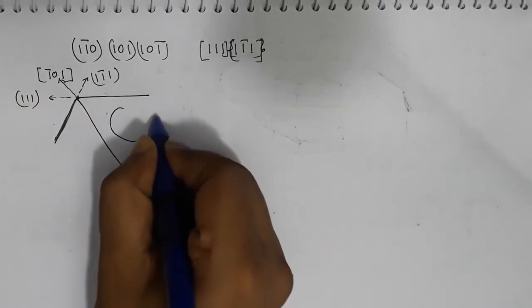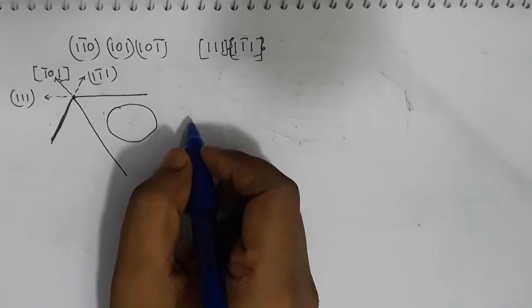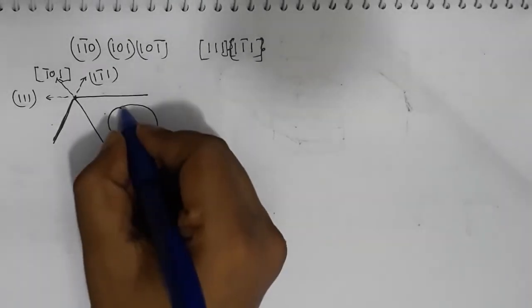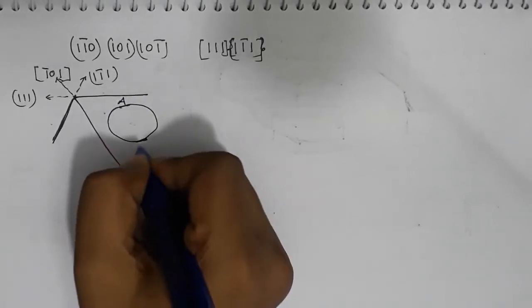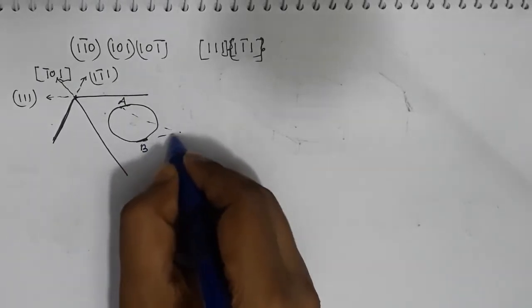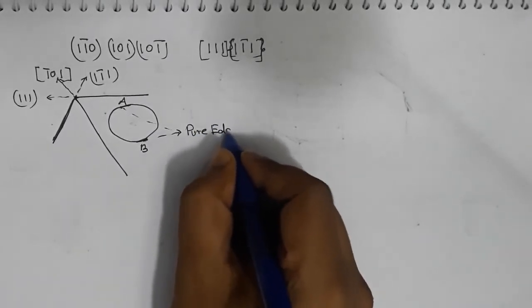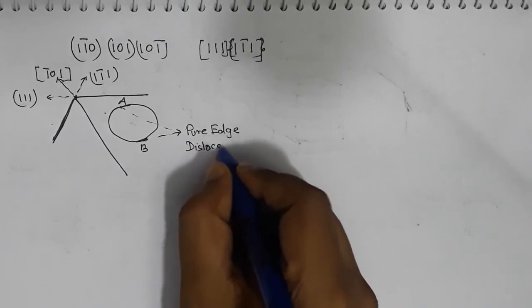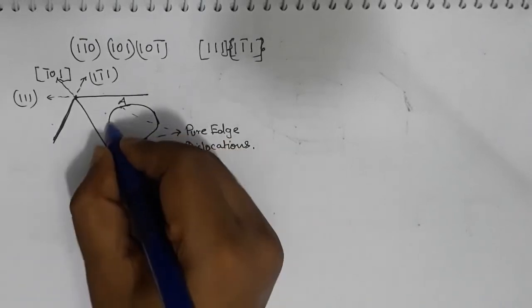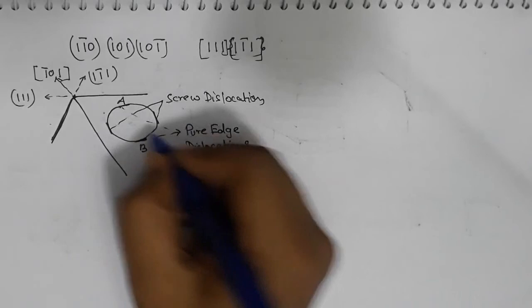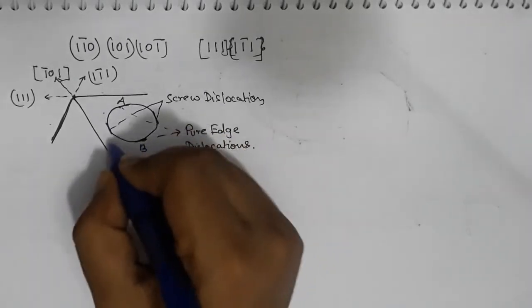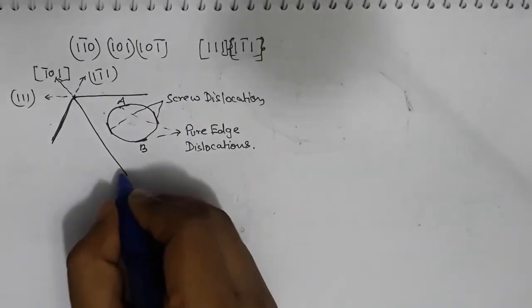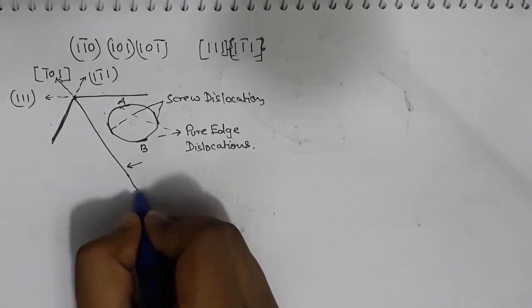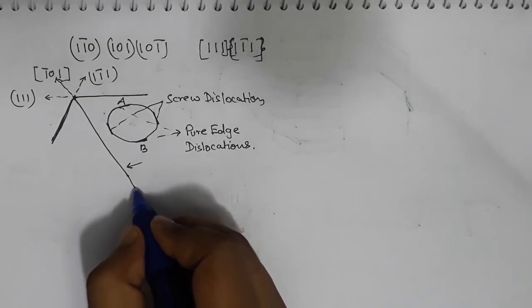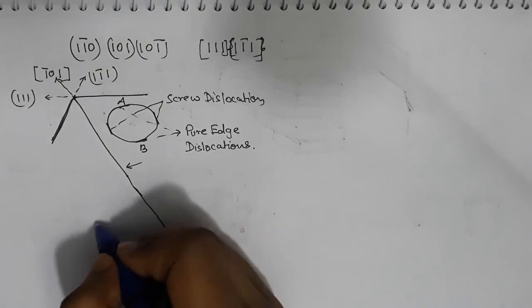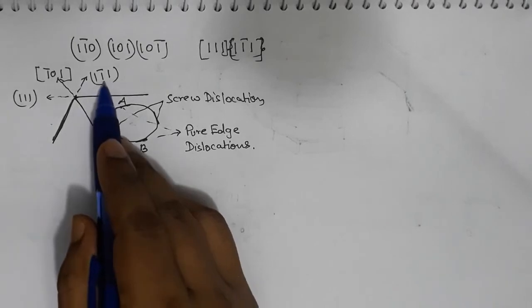Now you have a dislocation loop. The dislocation loop is such that here and here, let's call them A and B, these two are pure edge dislocation parts. And here and here you have pure screw, and the rest is a mixture of edge and screw dislocation. And this whole loop is moving, and it may appear that after some point of time, because the screw dislocation can actually move in another plane. Screw dislocation can move from one plane to another plane.